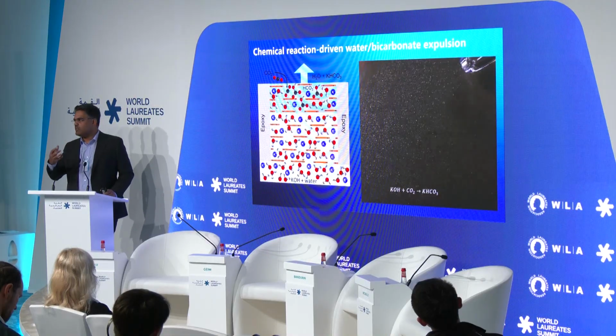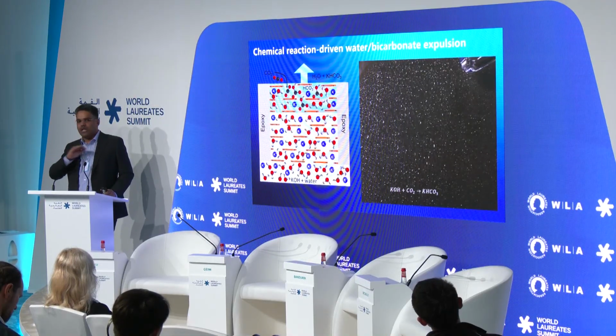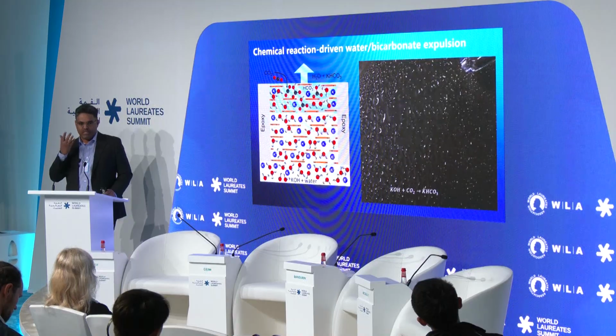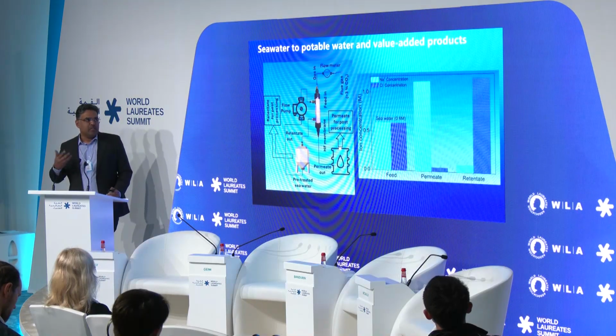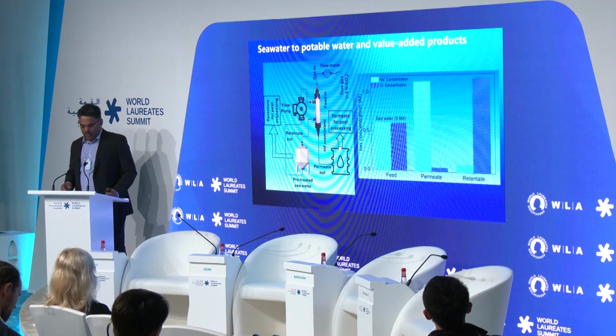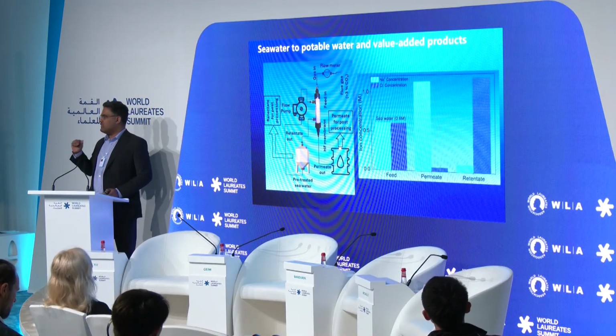If you remove the air or CO2 with, let's say, nitrogen or argon, no liquid comes out. So this membrane surface is dry. As soon as you put in a few percent of CO2, even air is fine, you get these big droplets of water coming out. It's not really pure water, it's carbonate or bicarbonate water. So now, thinking about applications, we started with the alkaline water.